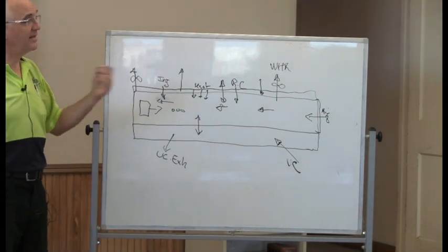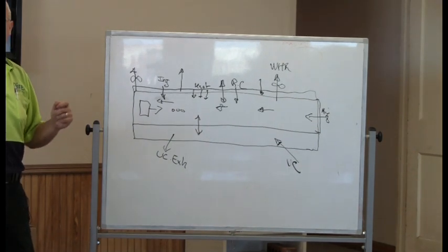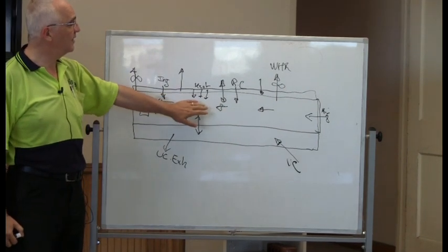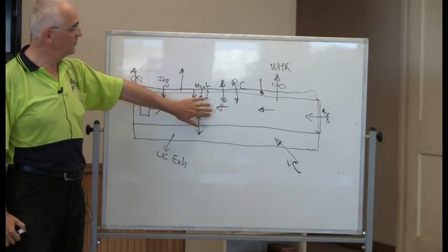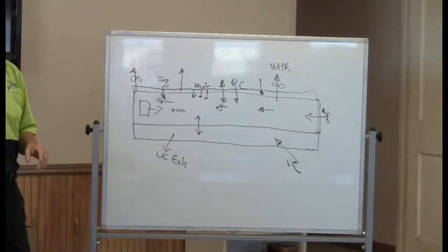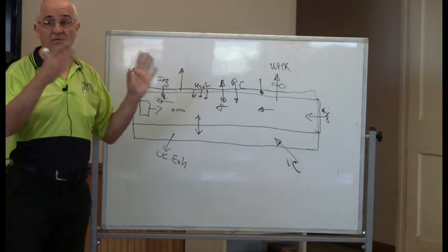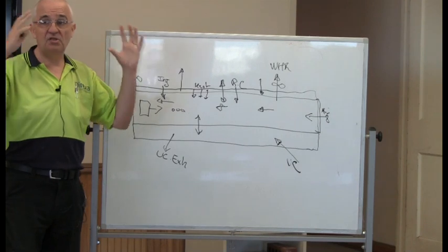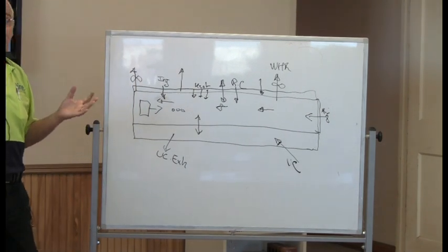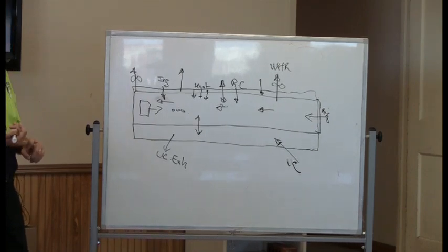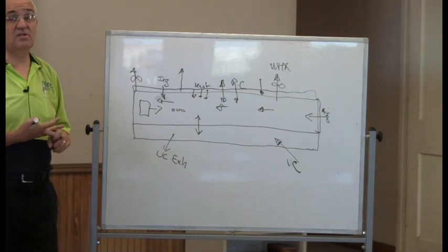And if you don't know those flows ahead of time, before you change the speed of a fan or the position of a damper or the position of several dampers which will interact against each other, you don't know what effect you create in the tunnel. And that quantity of air passing through the tunnel is critical. You were talking about color homogeneity between left, right, etc. If you don't have enough airflow through the tunnel, you don't create a good condition to distribute your heat properly. If the tunnel is lacking air in areas, the temperature is not going to move properly between the product. We rely on energy transfer by conduction and radiation, yes, but convection has a big role to play.